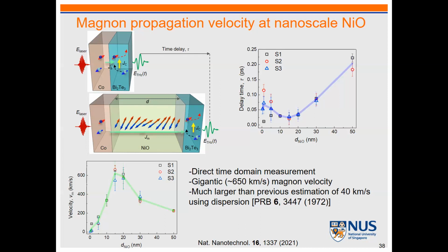It's not so accurate because we need to think about the conversion time from spin to magnon and magnon to charge. But we ignore those. We assume maybe that is even much shorter than the propagation time of the magnon. So as a first approximation, we extract this time delay as a function of nickel oxide, and we divide by the thickness of nickel oxide. That will give us the velocity. And you can see it initially increases up to about 600 kilometers per second, and then it decreases. And this speed range is extremely fast compared to the previous estimation of 40 kilometers per second using inelastic scattering measurement. Of course, it's a very old measurement and it's based on bulk samples, very thick.